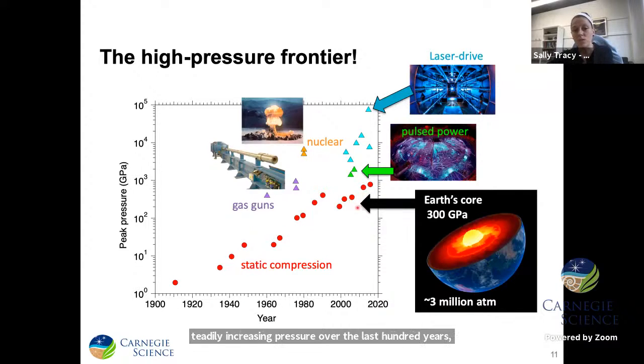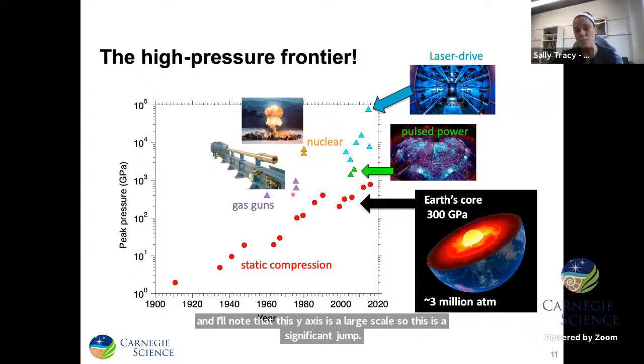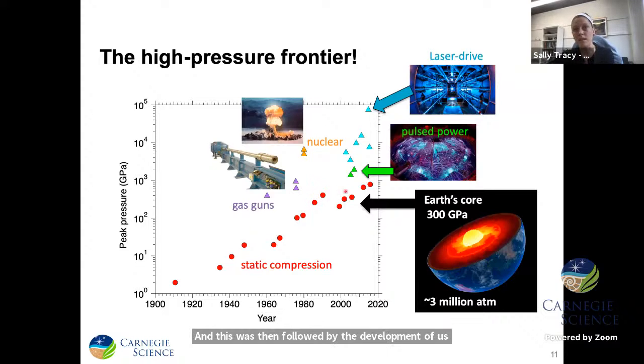And now it's fairly routine to achieve pressures of around 300 GPa, which is close to what we'd expect at the center of our own Earth. However, in around the 1960s, these gas gun methods came onto the scene, which are shown as these purple triangles here, which represented a big jump in the possible pressures that we could achieve experimentally. And I'll note that this y-axis is a log scale, so this is a significant jump. And this was then followed by the development of other dynamic methods, including nuclear and pulsed power techniques.